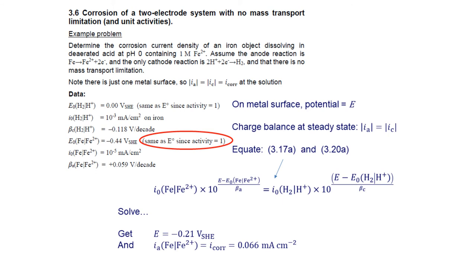So that means to solve this, we're going to be equating equations 3.17a and 3.20a, the Tafel equation for the anode process and the cathode process. And if we do that, we get some extended algebra. You should be able to solve, first of all, and you'd probably cancel out some terms and get the value of E. You'd find that the surface potential is minus 0.21 volts SHE. And then, knowing the potential, you can plug that into either one of the Tafel equations, and you can say that the anode current density for the iron dissolving, or equivalently the cathode current density for the hydrogen reacting, if we consider just the absolute value, those are equal.